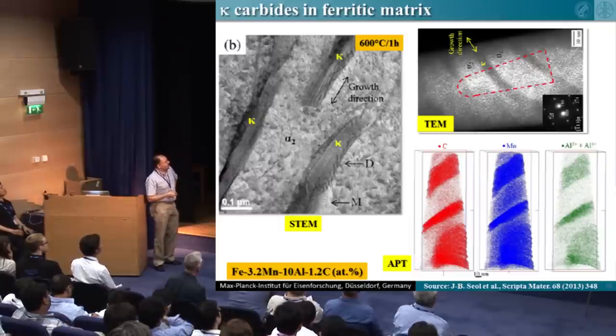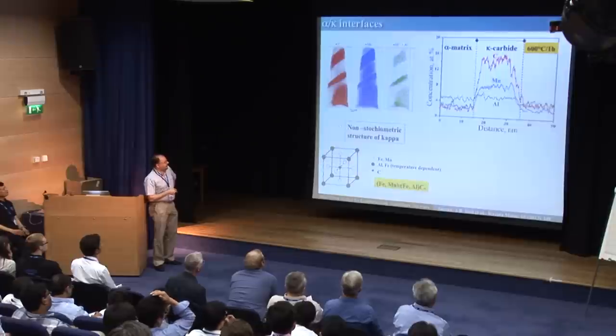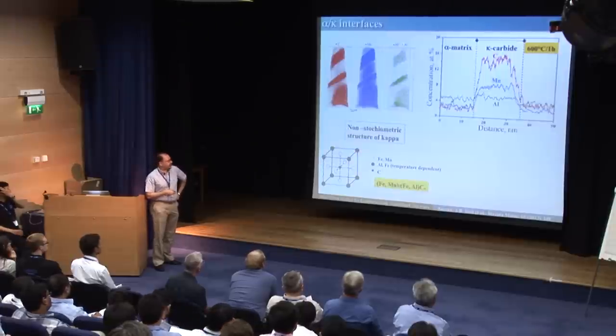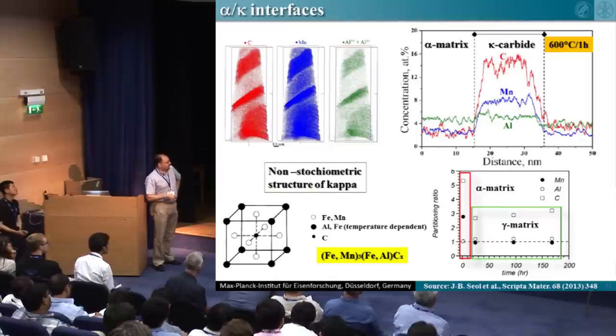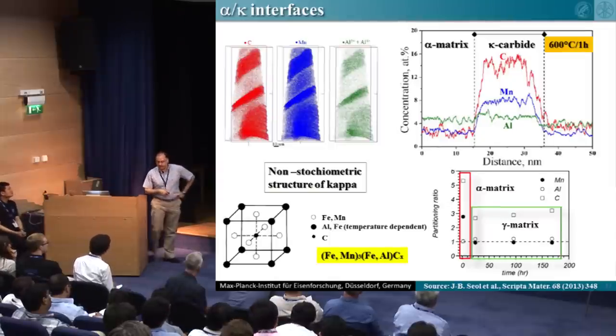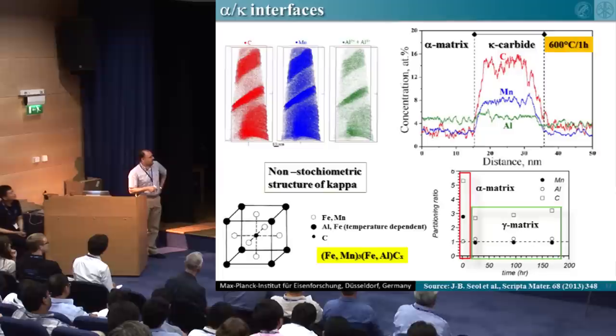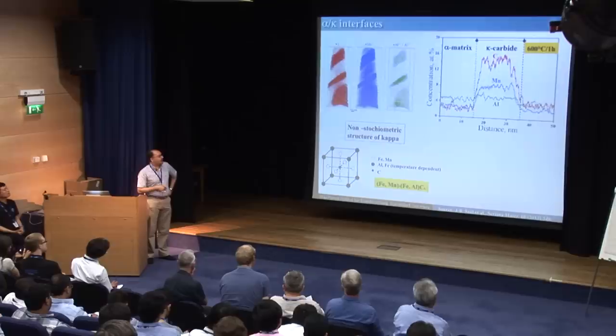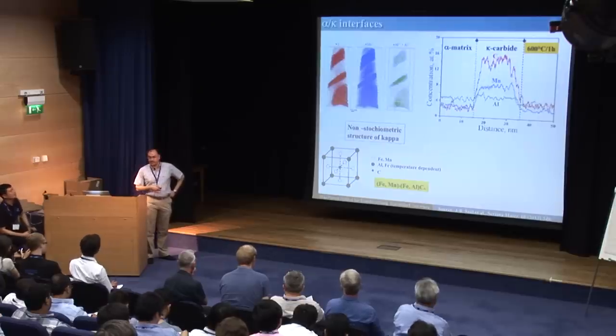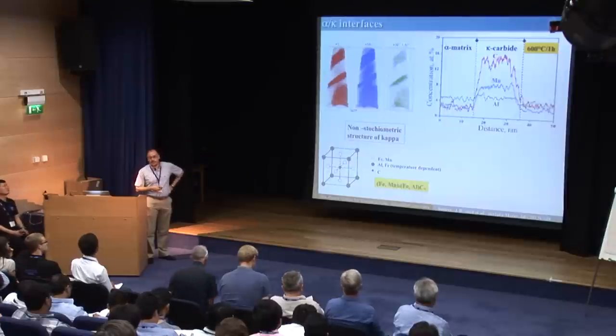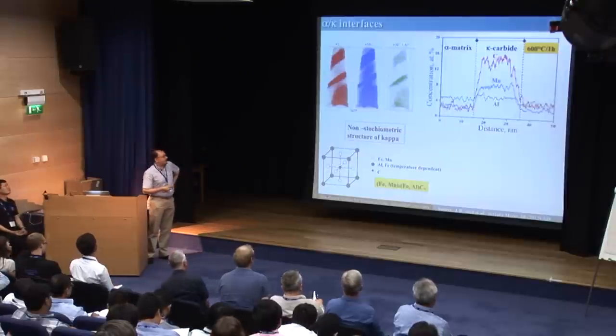APT analysis, furthermore, has revealed the non-stoichiometric structure of these particles. These authors propose this type of structure, where basically they suggest that iron is being substituted in the aluminum sites, and this is dependent on the temperature of annealing. So as you can see here, two analyses by APT of different steel grades have confirmed the non-stoichiometric structure of these particles. It's maybe not surprising because nobody has done it before with such kind of accuracy.